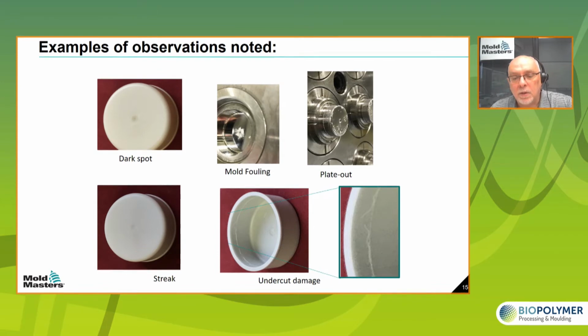The final two images show an undercut damage. This material is a very robust and tough material. It is more of an engineering material than a commodity material. It's not something you would typically use for a closure. And you can see that as this part is being pushed off the core, the undercut is being damaged because that material is not very flexible. So again, that's a good point to highlight on this material, that if you're designing a mold for it, you're not going to be able to use an undercut on that mold design without getting damage on that undercut.